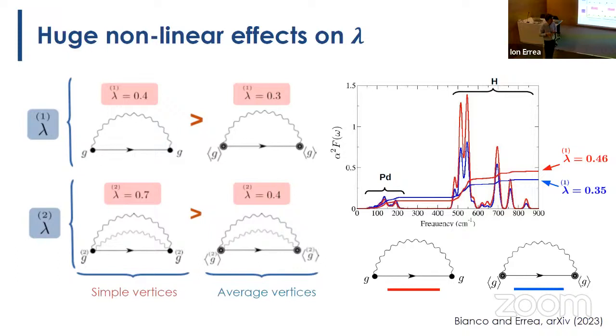So yes, in principle, it's good. Then you have other types of theories for calculating the thermal conductivity, but I'm not going to enter into detail. You can just solve the Boltzmann equation in the simplest approximation, or you can do more complex approaches based on Kubo formulas and so on. But in the end, the ingredients are the same. In systems where the harmonic approximation gives you unstable phonons, you cannot do the standard perturbation theory to calculate thermal conductivity, and you need to go to these machineries or similar things. That's the case that we did in tin selenide, for example in the high temperature phase.